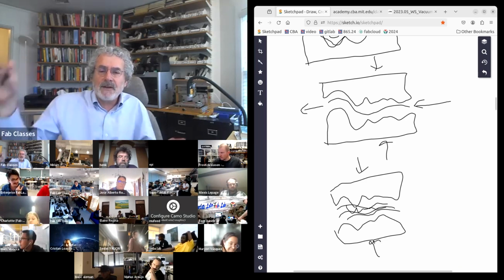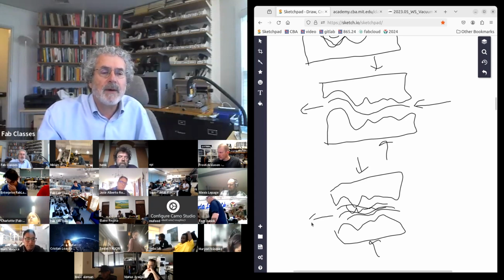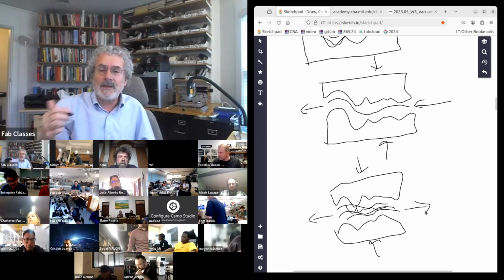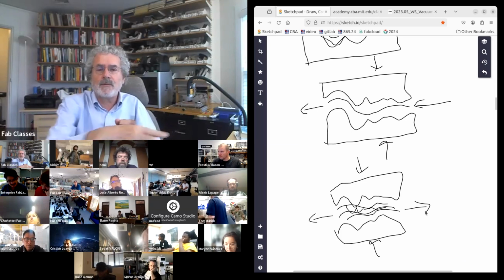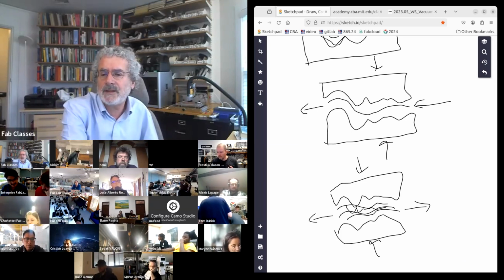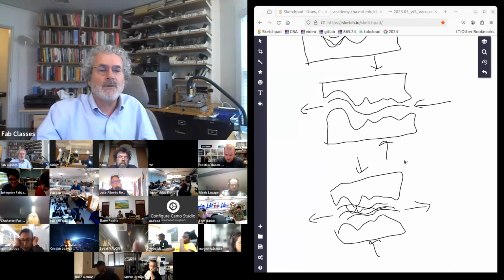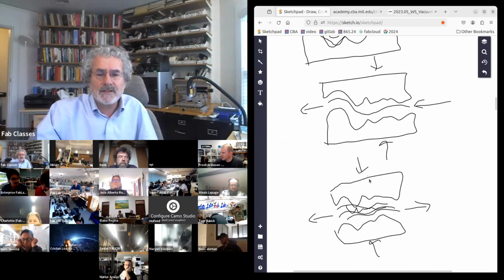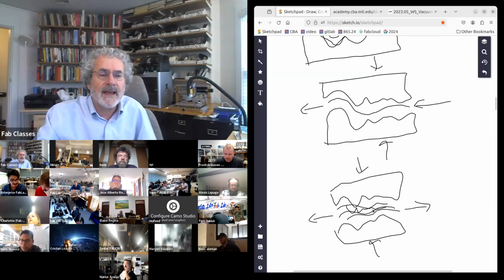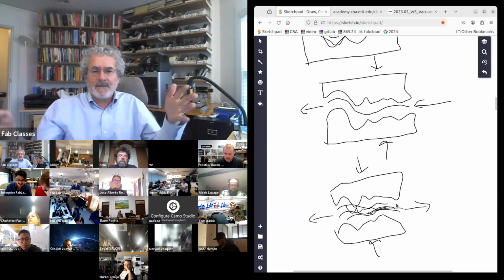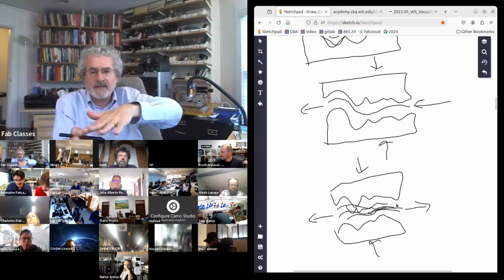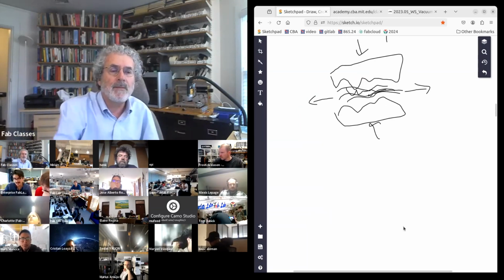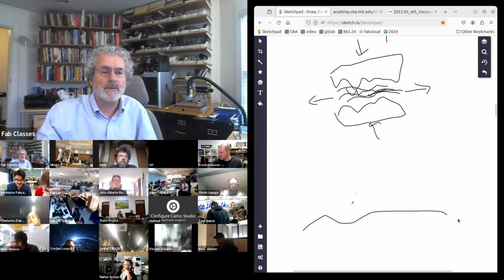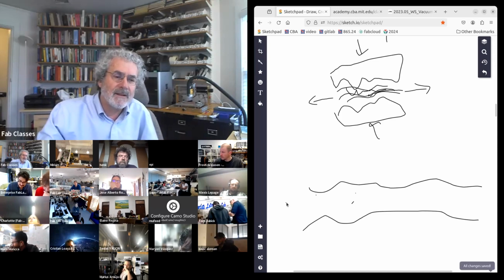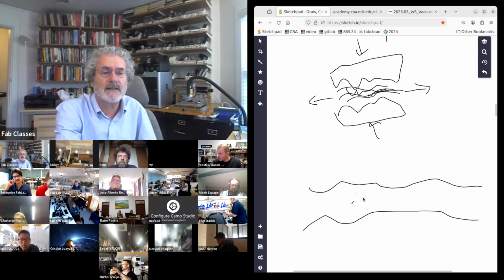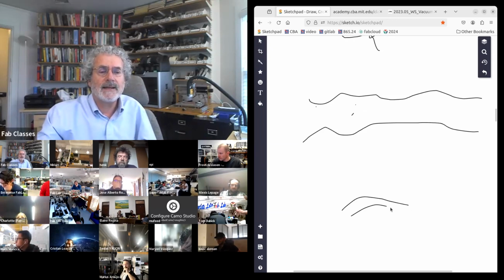If the mold isn't very large, I can squish the epoxy resin out the sides. So in resin transfer molding, you actually force the resin through the mold. In a kind of beginner resin transfer molding, you squish from the top, and then the excess resin migrates through and goes out to the sides. And if the mold isn't too large and the force is large, you can do a good job with that. The problem, again, is if you have a really big mold, like say you're making an airplane, it's hard to get the excess resin all the way out to the sides. So then what's happening is you have your plies in the mold.